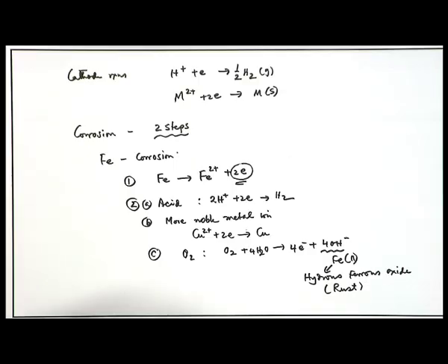So when corrosion is there, this hydrous ferrous oxide will be produced over there, and this hydrous ferrous oxide basically has more volume. Okay. So it will have a larger volume, so it will just bulge out of the surface. Therefore, it will look as if some blister-looking thing is on the surface, across the paint. So if you give a little pressure, then it will break, and then the paint will also go, and ultimately the good look of this painted surface is lost.